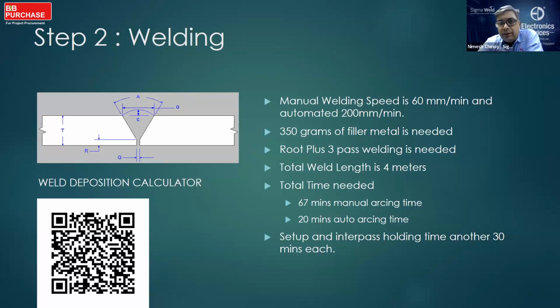Typically, if you want to do a 1 meter weld for an 8 mm thickness, you need to have 3 passes, root plus 3. That means a total of 4 passes. So 1 meter results in 4 meters of welding. Total time needed is 67 minutes by manual and 20 minutes in automation. Setup time and interpass holding time, another 30 minutes each will be required because you cannot weld consecutively back to back. Otherwise, you have overheated material and it can bend or distort.